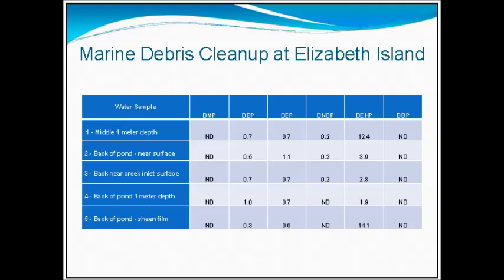And if you look at that, you'll notice that DEHP turns out to be the major contaminant that we saw in the system. Most of the other contaminant levels are just about at the detection level, but DEHP is significant in that particular location, and the highest concentration here is in the film. These are parts per billion levels, but they're very, very low. However, when you actually look at the water concentration, it tends to be much lower than, say, concentrations in the plastic material itself or in organisms that are exposed to these concentrations.